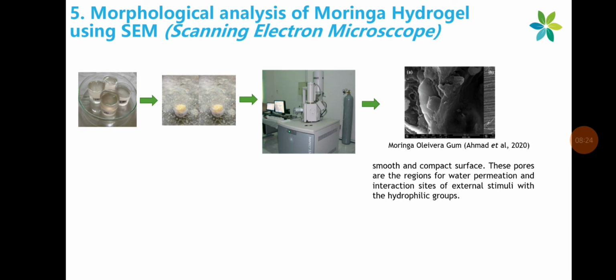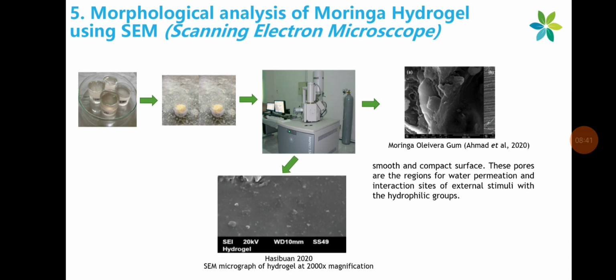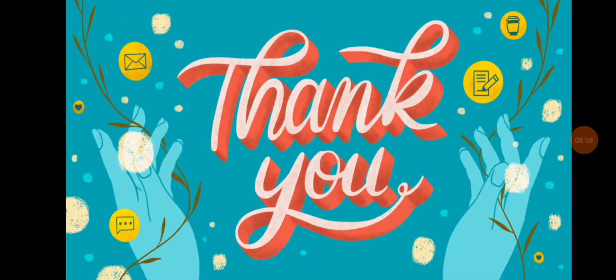The research from Ahmed showed that the Moringa oleifera gel exhibited a smooth and compact surface. These pores are the regions for water permeation and interaction sites of external stimuli with the hydrophilic groups. The next research is from Hasibuan 2020. The micrograph shows that the surface of the hydrogel looks neater and smoother because the extract has been evenly distributed through the hydrogel network.